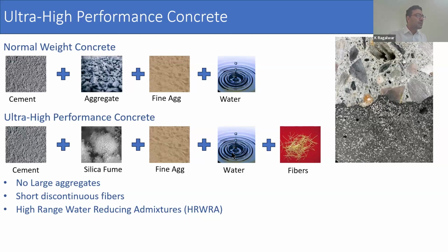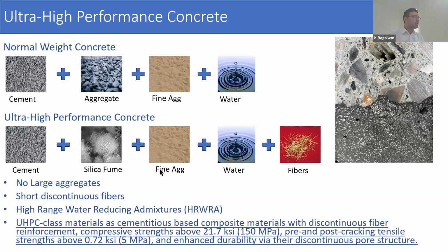So with very low water content, it's difficult to mix and have workable concrete. So that's where admixtures come into picture. So UHPC class materials are cementitious based composite materials with discontinuous fiber reinforcement. Compressive strengths of above 21.7 ksi, which is equivalent to 150 MPa, and they have a pre and post cracking tensile strengths of above 5 MPa and enhanced durability via their discontinuous pore structure.